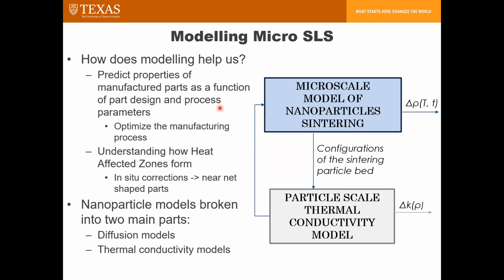So there are two main advantages to modeling the sintering process. The first is what we've discussed, which is in trying to correct for the heat affected zones that form during sintering. So if we can predict how the heat affected zones are going to form, then we can make in situ corrections to the laser heating profile to account for how heat will spread. And this will get us more towards the direction of achieving near net shape parts.